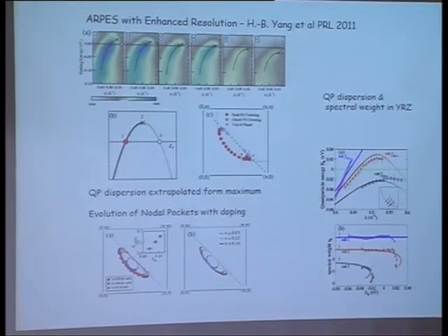So they can measure up to this point, and then they extrapolate using a simple parabolic extrapolation to get a possible second crossing of the Fermi energy at this point 3, which is just inside this zone. And you see this form that we have also has this loss of weight. This is just like in a Bogoliubov pairing quasi-particle.